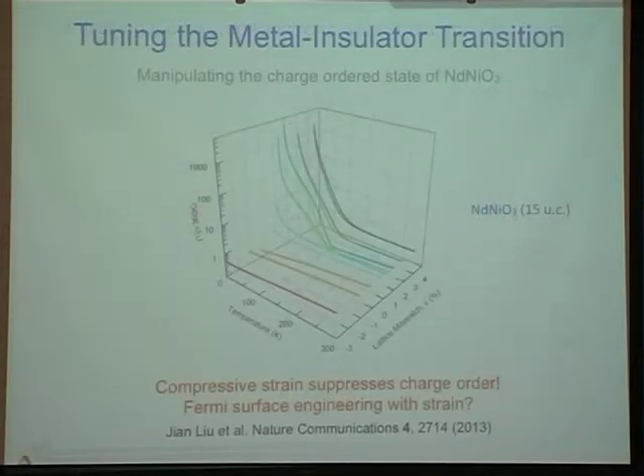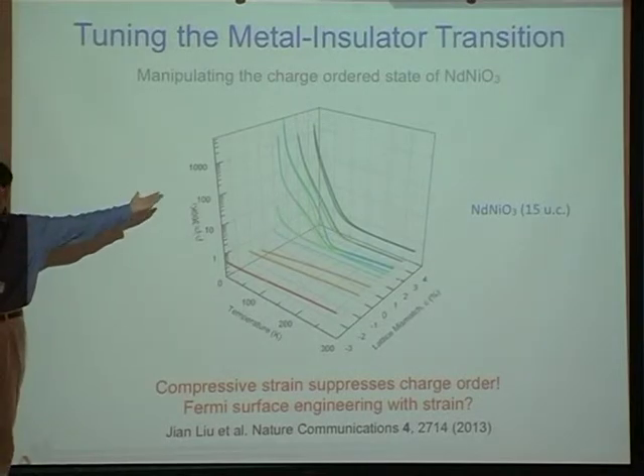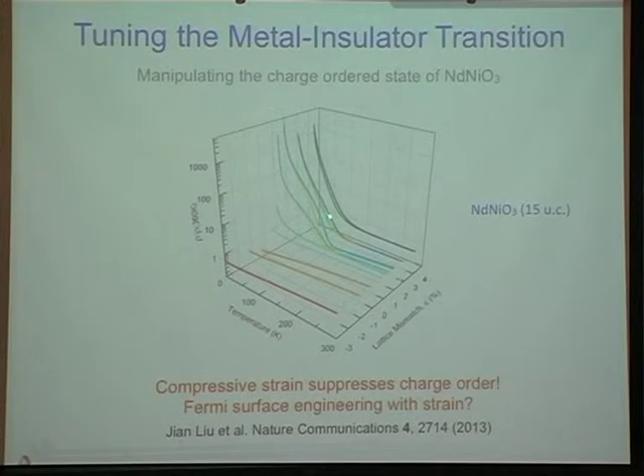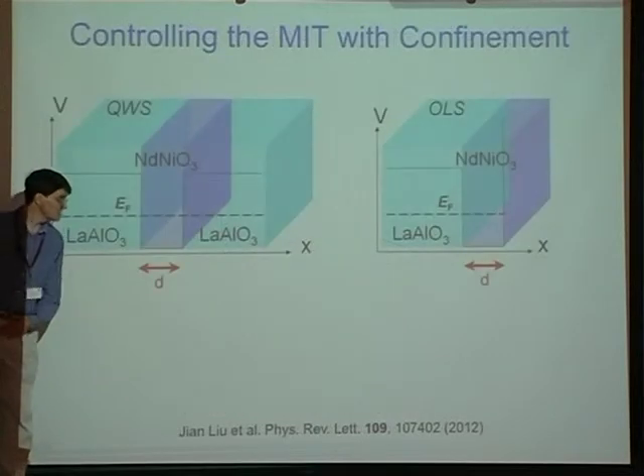So the first thing we did was actually we studied the dependence of strain on just a single layer. And what we found was, under tensile strain, this material maintains a first-order metal-insulator transition. But as you apply compressive strain, you completely suppress that metal-insulator transition. And you have this very nice crossover through some very interesting regions here. So then the question is, well, if I go from here to here and I completely kill that insulating state, can I bring it back in a heterostructure? And the answer is yes.